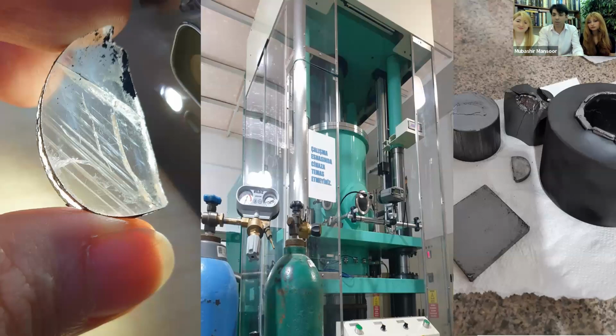Exactly. So what we did, we thought, well, this is such an interesting phenomenon that we would like to do more experiments on it. And a few months ago, we came together with Ted Temelis here in Istanbul, and we did some of these experiments under pressure, the heat treatment experiments under pressure, using this device that you see in the center. This is actually a spark plasma sintering machine, which this shaft over here can create a very high pressure in the center. So we applied the kind of pressure which is being applied in Korea, the 100 megapascals, and we placed the sapphires in rather similar conditions that they do. And look at what we saw.